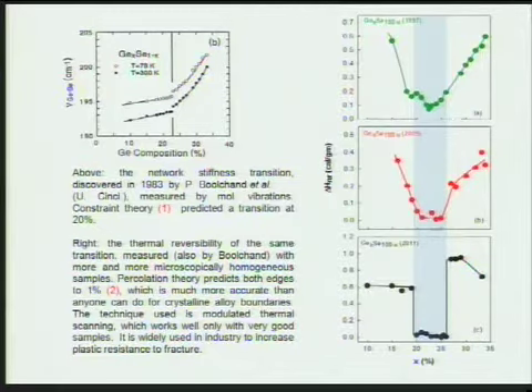And this intermediate phase is perfectly reversible. You notice that what we have plotted over here on the ordinate is the non-reversible entropy of the glass transition, which turns out to be very small in this narrow window. Now that narrow window is very important because it also happens to be the window where, I'm not showing it, the stress is very small. And that narrow window is what makes it possible to build skyscrapers out of window glass without any reinforcing rods in them.